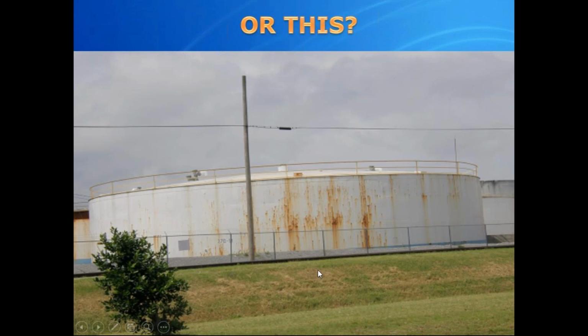And this beautiful tank that we're looking at, there's poor surface preparation resulting in corrosion at the weld seams. You have pinhole corrosion due to poor spot and sweep abrasive blasting, undercreep from damaged original coatings, and surface rusting from the shell on the handrails. As you see these handrails here with the corrosion, the rust bleed running down.